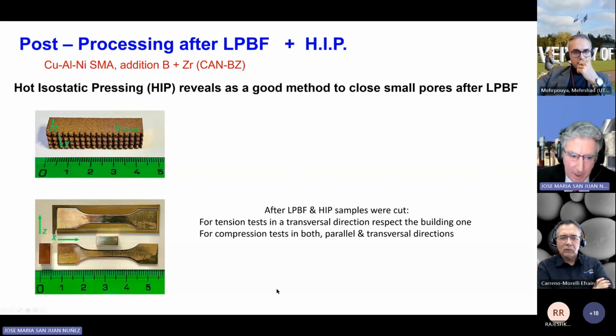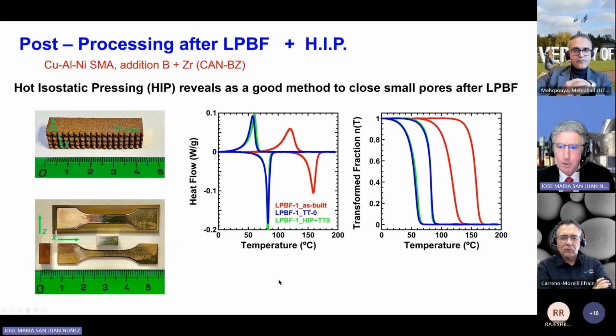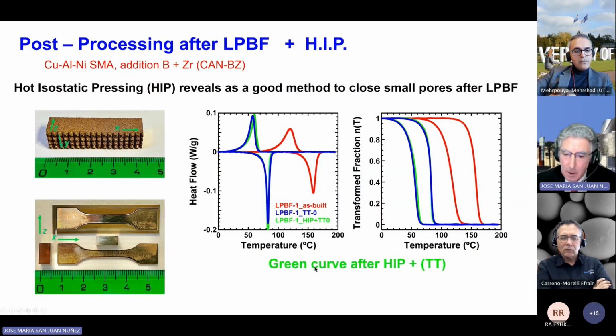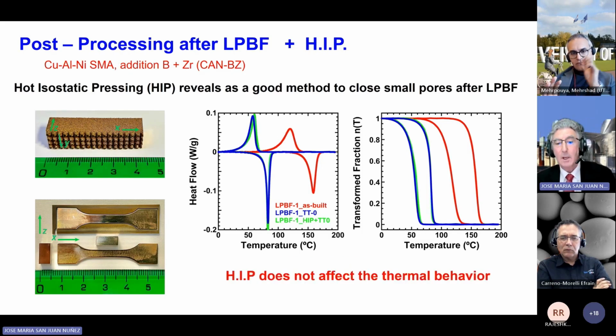the thermomechanical properties. In what concerns the transformation behavior, I reproduce again the as-cast material after thermal treatment, and the green curve corresponds to the material after HIP and thermal treatment. So we can say that hopefully hot isostatic pressing does not affect the thermal behavior of the material after laser powder bed fusion.